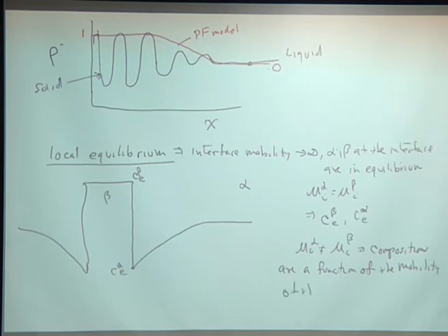You might think this is a digression, but it turns out to be really important in terms of a phase field model. As the mobility gets slower and slower, it gets harder and harder to move the interface. There's more and more drag. And so the diffusion rate of solute becomes faster or easier. And so in the limit where the mobility basically goes to essentially zero, the solute field looks like this.